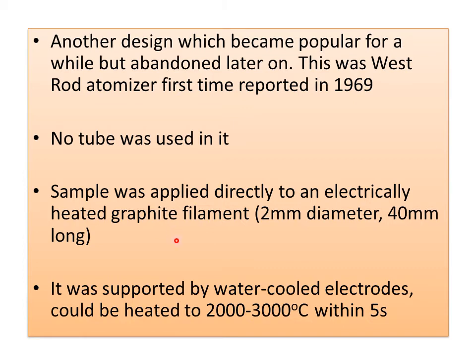And what were the dimensions of this graphite filament? It was 2 millimeters in diameter and the length was 40 millimeters. Further, it was supported by water-cooled electrodes, definitely to provide heat. So it was able to reach a temperature between 2000 to 3000 degrees centigrade within 5 seconds. But as mentioned earlier, this design also couldn't get much popularity, so it was abandoned.